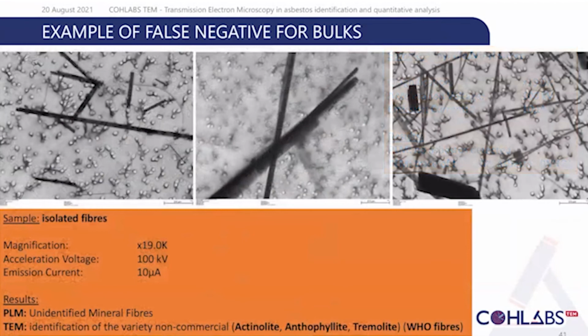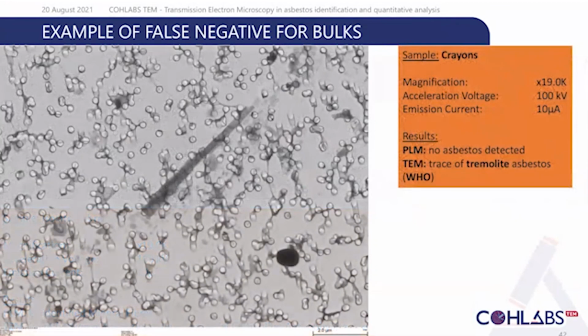For this one, under the PLM, we found unidentified mineral fibers, and that's mainly because those three pictures here represent the three non-commercial asbestos fibers. With the TEM, we were able to differentiate which one was actinolite, anthophyllite, and tremolite fibers. Another example of false negative for bulks, this one in a different sample, we were analyzing crayons, and the PLM didn't find any asbestos, while we found trace of tremolite using TEM analysis.